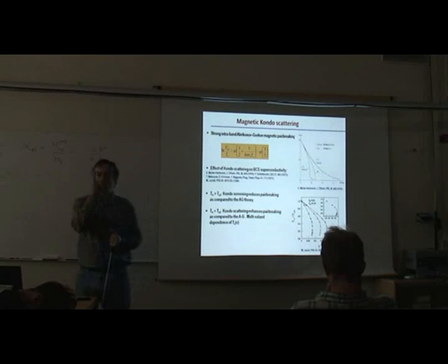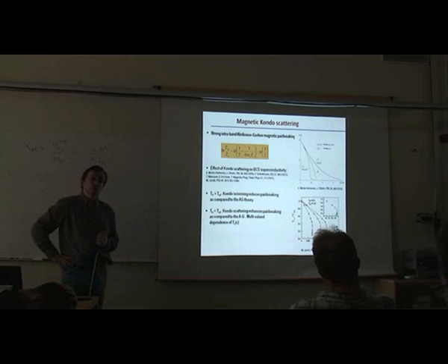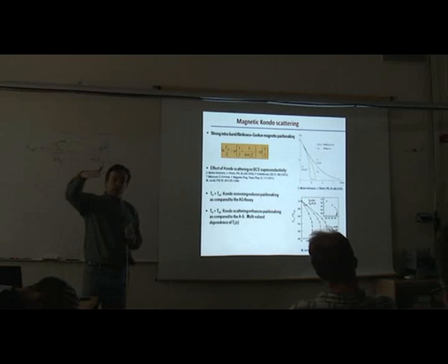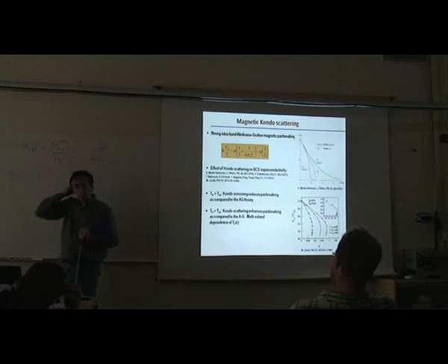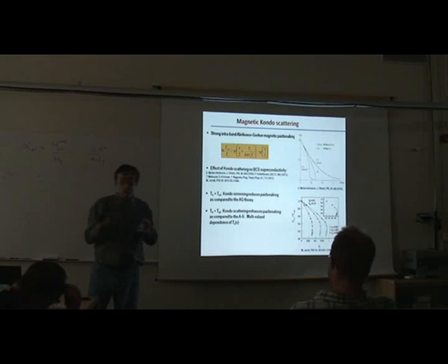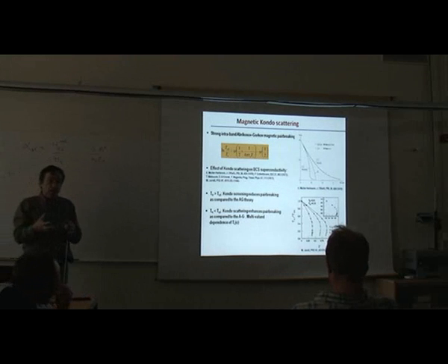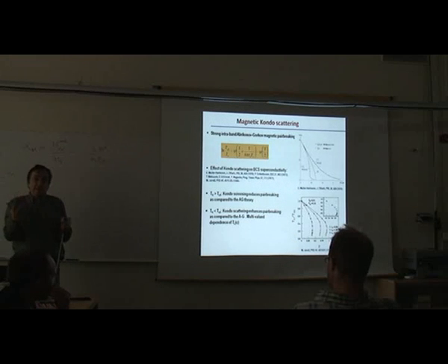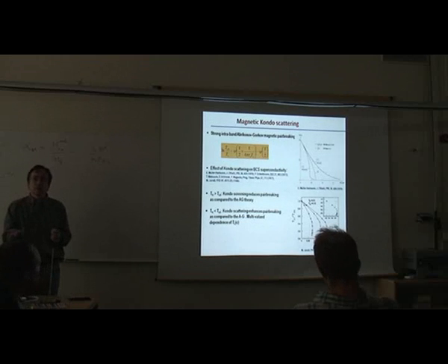Well, that we don't know. No, I mean, we see the strong effect. I mean, because we see resistivity shows this logarithmic upturn, telling us that there is a spin flip. Otherwise, you wouldn't see this logarithmic upturn in resistivity. So we can only speculate that in this material, we simply add magnetic impurities, and they change polarization of the band which does the coupling. They simply enhance the susceptibility, you can say. And the coupling constant is proportional to susceptibility. So it's really a non-BCS situation.